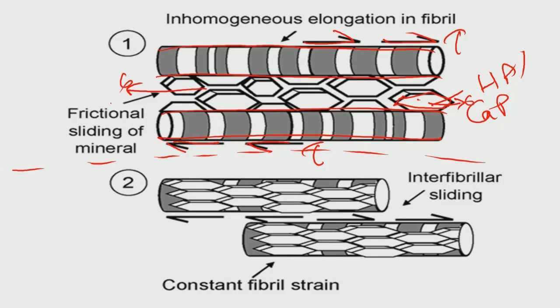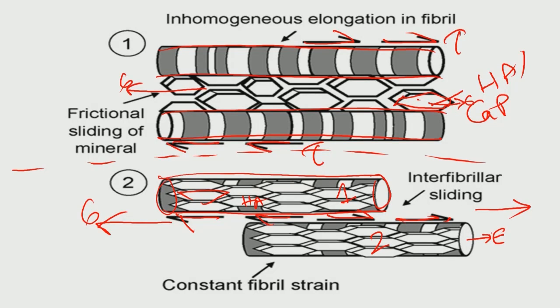The other scenario is that you have a collagen bundle, and within this collagen bundle you have the hydroxyapatite platelets, which are contained well within it. This hydroxyapatite loaded collagen bundle will experience the global tensile stress. So automatically there will be interfacial sliding, which will allow collagen bundle 1 to slide over collagen bundle 2. And therefore, this will have a very constant fibrillar strain which will be experienced by the hydroxyapatite.